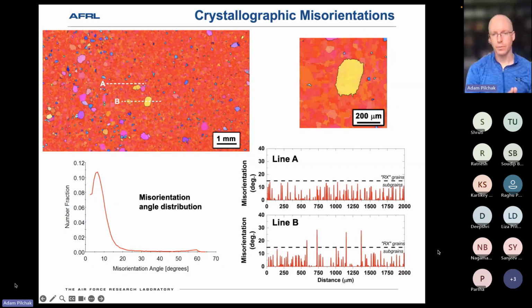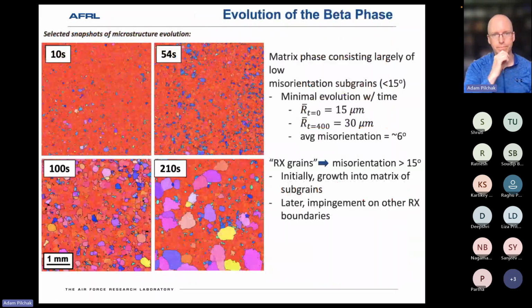So for the purposes of this work, we drew the line at 15 degrees as a way to just classify what was recrystallized versus what is not. That was aided by looking at the misorientation angle distribution of the subgrains only, which shows a peak around 7-8 degrees and then decays rapidly toward about 15. And so we drew that as our distinction for the subsequent work.